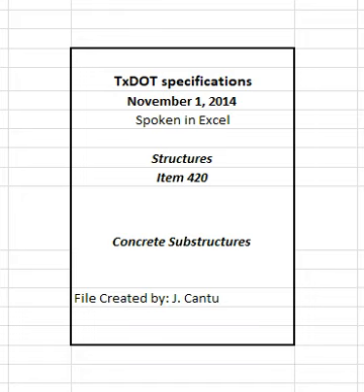of the mat. Provide polyethylene sheeting that is at least 4 mils thick and free from visible defects. Provide only clear or opaque white sheeting when the ambient temperature during curing exceeds 90 degrees Fahrenheit or when applicable to control temperature during mass pours. Provide burlap polyethylene mats made from burlap impregnated on one side with a film of opaque white pigmented polyethylene, free from visible defects. Provide laminated mats that have at least one layer of an impervious material such as polyethylene, vinyl plastic, or other acceptable material, either as a solid sheet or impregnated into another fabric, and are free of visible